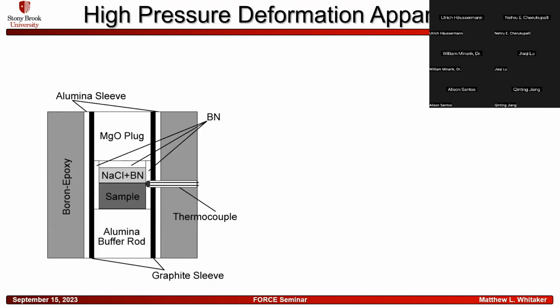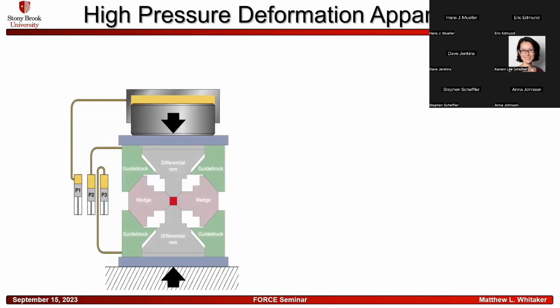So when we talk about the high pressure deformation apparatus, we have the simple D-DIA configuration that we have here, where we have our sample, and this gets put into our D-DIA, and again we can advance the differential rams on the top and the bottom and deform our sample and study it that way. In the D-DIA geometry, we have a relatively limited pressure range, where we can go to about 10 or 12 GPa max easily. It can be extended a little bit further, but it becomes a much more difficult experiment.